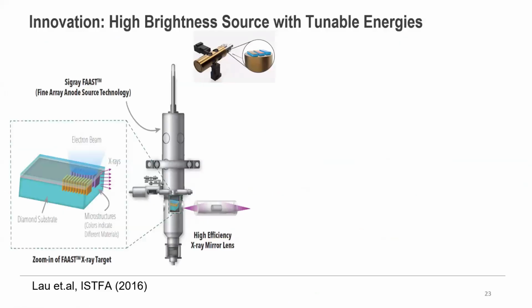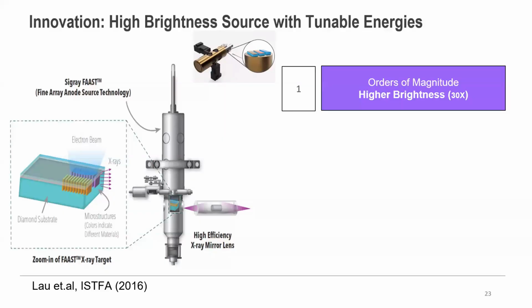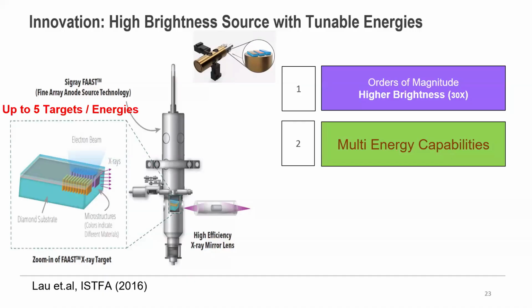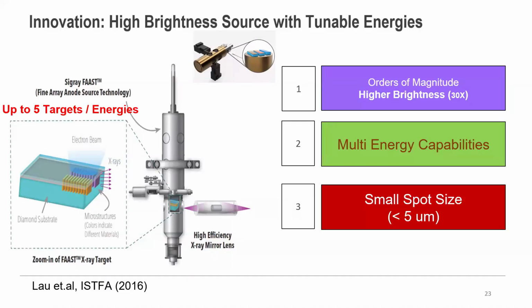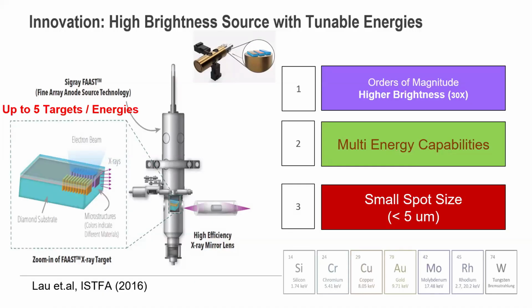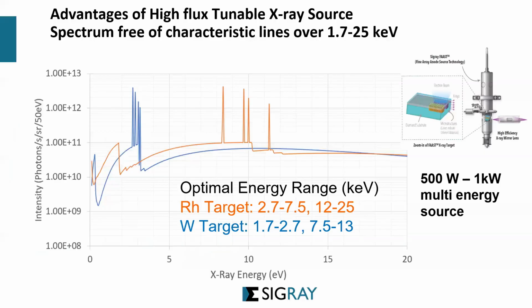And one of the innovations is that of the X-ray source that has tunable energy. Not only does it have very high brightness, it gives you the ability to have multiple targets and a small spot size, with the choice of numerous targets available. And that is important, especially in XAS, where you are not using the characteristic lines of an X-ray spectrum. In fact, that is the area we have to avoid. We have to use the Bremsstrahlung,